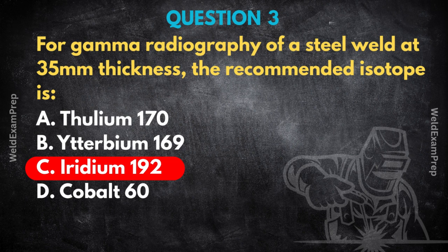On the flip side, cobalt 60, option D, that's for thick sections like 50 millimeters up to maybe 200 millimeters. Its energy is much higher. It would blast through 35 millimeters, yes, but the energy is too high. You'd get a very low contrast image, kind of washed out. You could easily miss smaller flaws. So matching the isotope energy to the thickness, absolutely critical for a reliable NDT result. That makes perfect sense, optimizing the tool for the job.